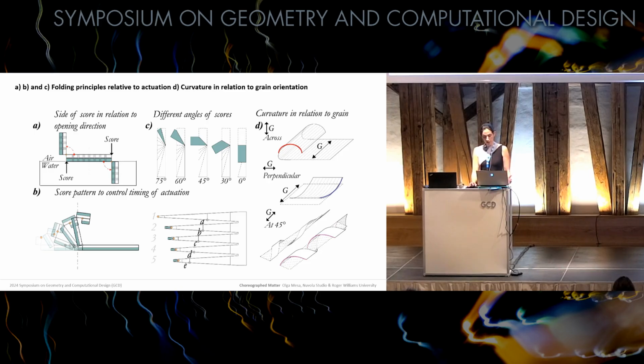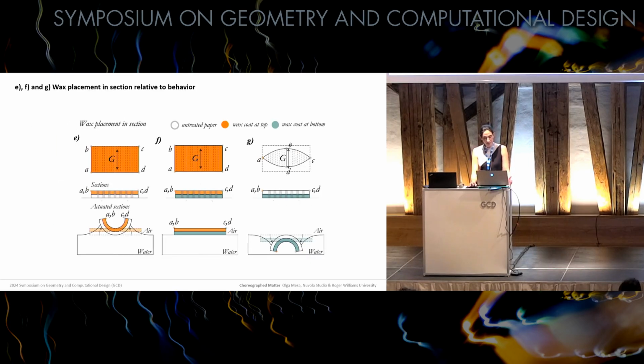The difference in the way of bending and spiraling were observed and recorded depending on the orientation angles of the fiber. Also, wax patterns were selectively applied to tune the material's reaction to water absorption. Depositing wax on the top and not the bottom induces a curling action upwards. Applying it to both stabilizes the flat stage, and applying it to the underside produces downward curling into the water.